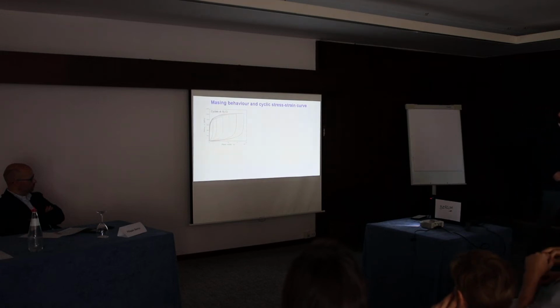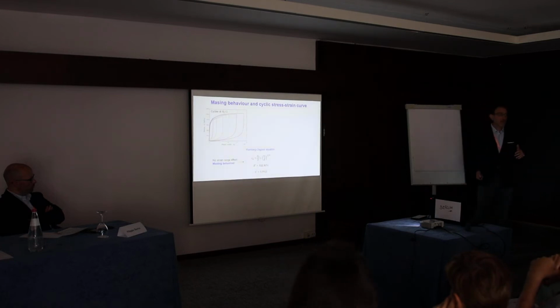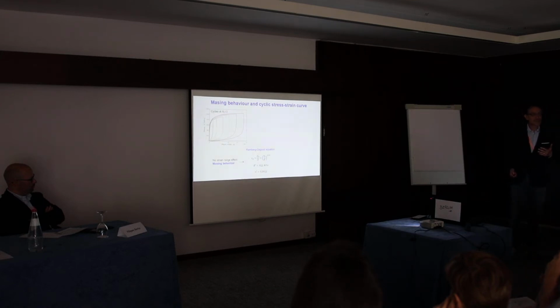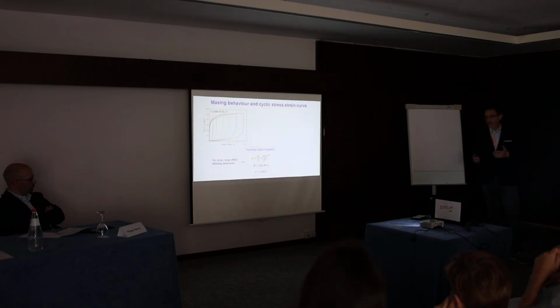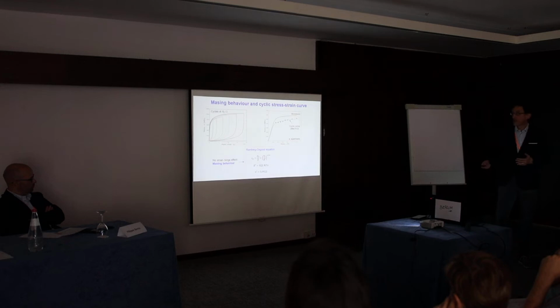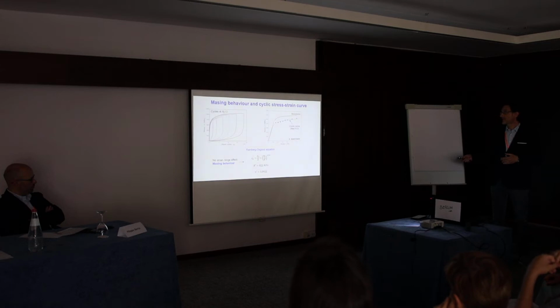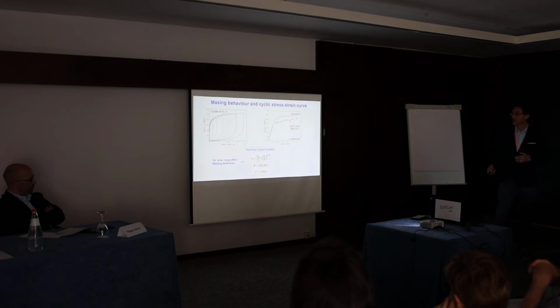Now, we also investigated whether this material has a Masing behavior, and it has. In fact, we translated all the stress-strain cycles to the origin, and as you can see, it is not perfect, but it is almost a Masing behavior. Therefore, first of all, we also tried to fit the cyclic stabilized stress-strain curve according to the Ramberg-Osgood equation. Here you can see the fitted parameters, and then we also compare the monotonic stress-strain curve, the experimental cyclic stress-strain points, and the fitted Ramberg-Osgood curve.